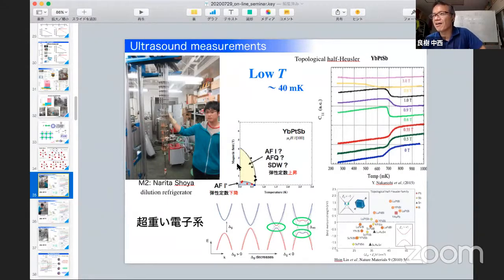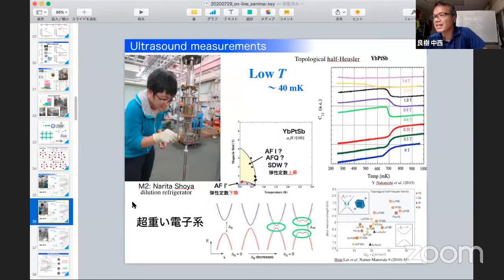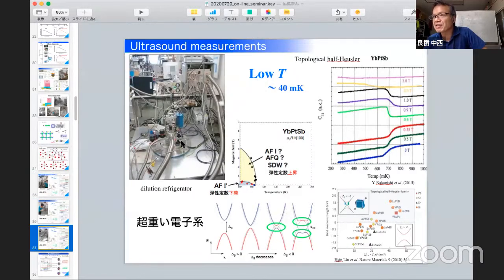So I must say, we have a dilution refrigerator. This is a special experimental apparatus which enables us to go to low temperatures down to 40 millikelvin. This is the inside of the dilution refrigerator, and combined with magnetic field, we can conduct ultrasound measurements in a field up to 10 Tesla and at temperatures down to 40 millikelvin.